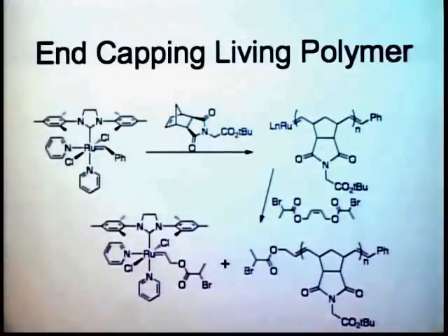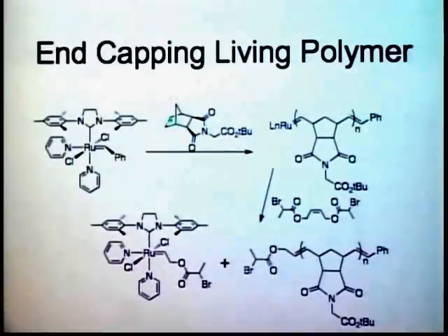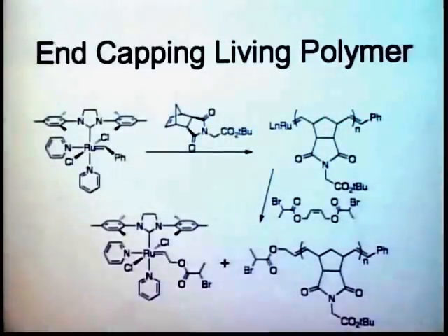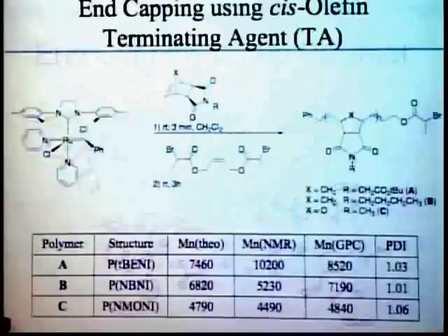So we end up having 3 kinds of double bonds in this system. We have the double bonds here, which are the most reactive. We have these double bonds, which are the second reactivity. And then we have the double bonds in the polymer, which are the least reactive. And they're least reactive because they have these bulky groups in the allylic positions. So they're blocked sterically.